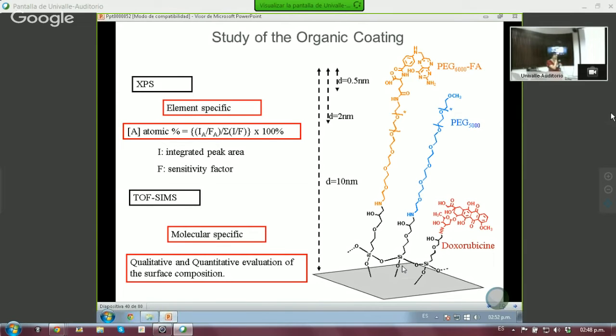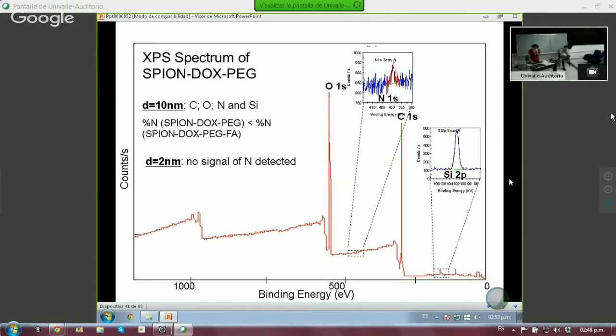So you see what's on the surface, but it's very, very difficult. It's possible, but takes lots of time to come up with precise numbers. But all we wanted to check in our case is to make sure that the drug didn't make it to the surface, so we could look for the elements of the drug. So this is the spectrum of SPION with DOX. Again, DOX is the drug, and the PEG.